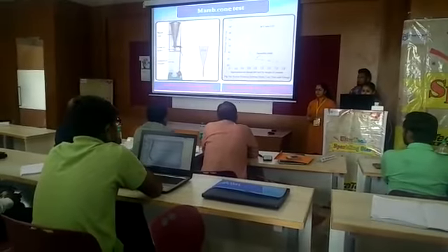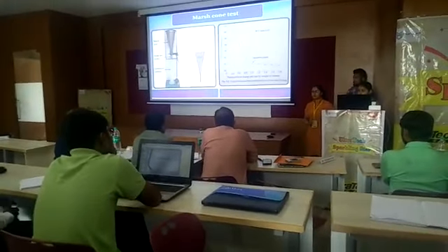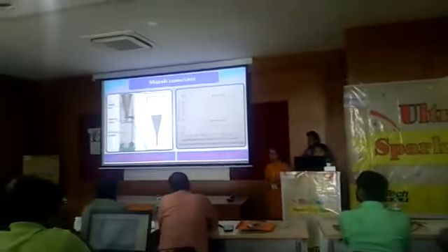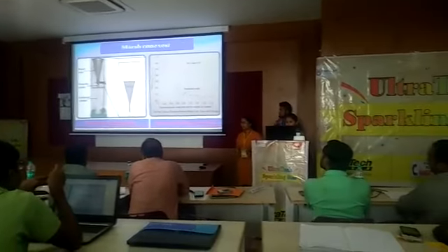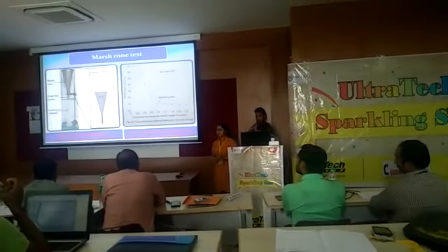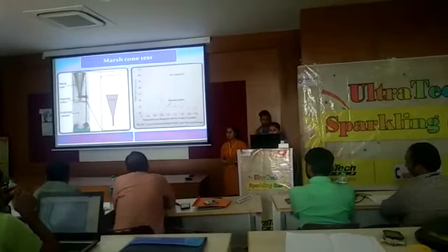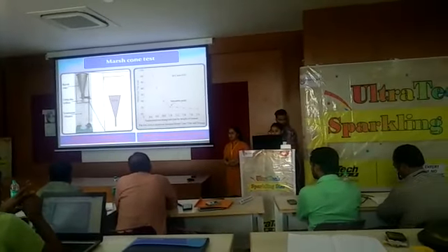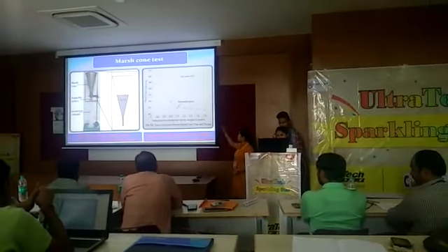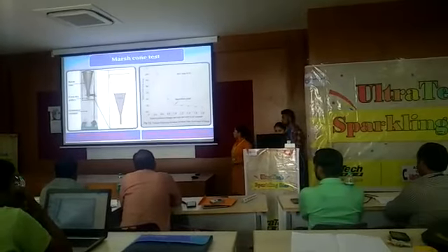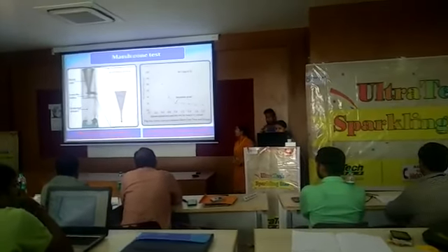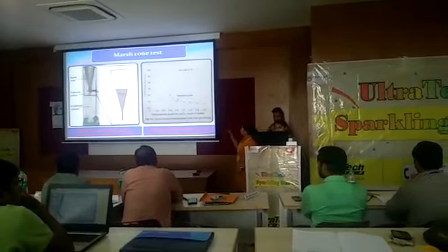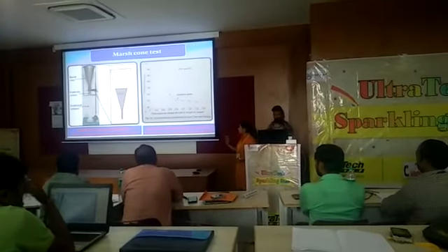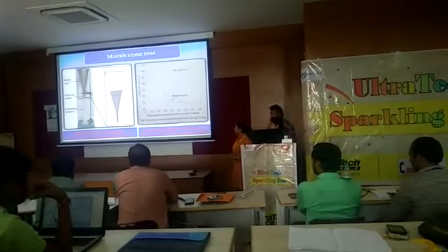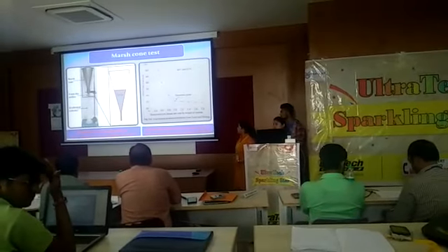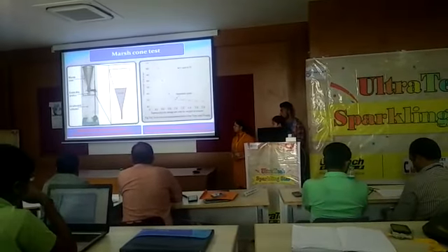Then take the slurry and pour it in the Marsh cone, closing the aperture with a finger. Start the stopwatch and at the same time remove the finger from the aperture. Repeat the test with different dosages of plasticizer and plot the graph connecting Marsh cone time in seconds and dosage of plasticizer or superplasticizer. The dose at which the time is the lowest is called the saturation point and is the optimum dose for that brand of cement and plasticizer for that water cement ratio.